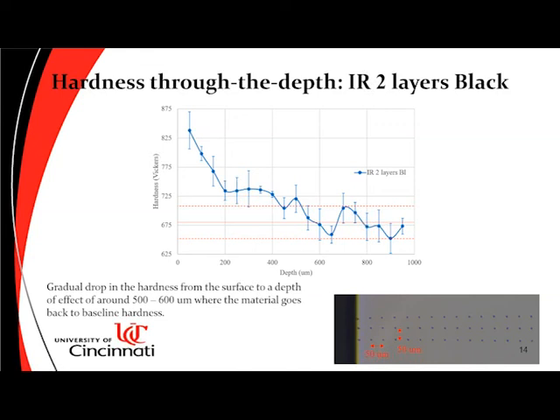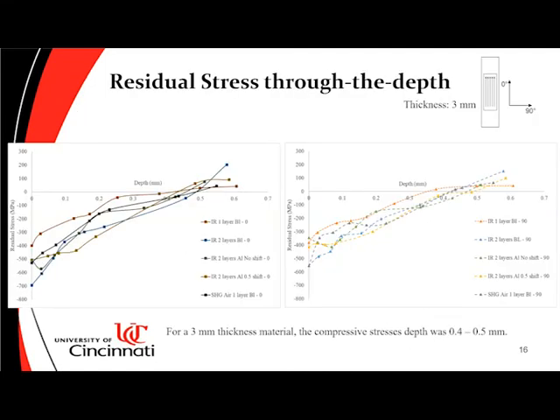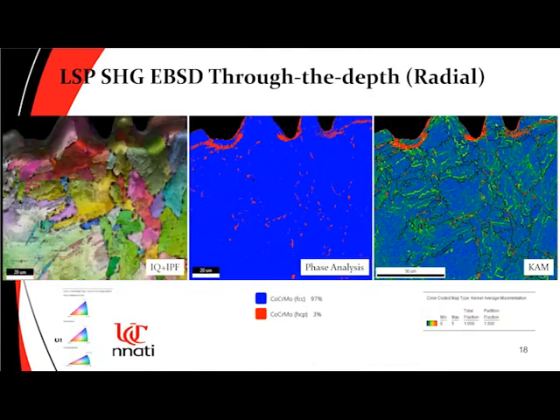The second question was what information we get from the KAM maps in the EBSD, and how it is related to the LSP-induced modification. So when you showed the EBSD maps, what are you trying to say? So here we're talking about strain. The KAM map will show the amount of strain in the sample, and the LSP will input some amount of strain into the sample. So over here, we can see there's a lot of strain, especially near the surface where we have the red. If I compare this to the AM build, you would see more blue without much strain.